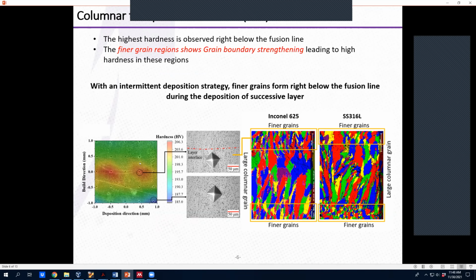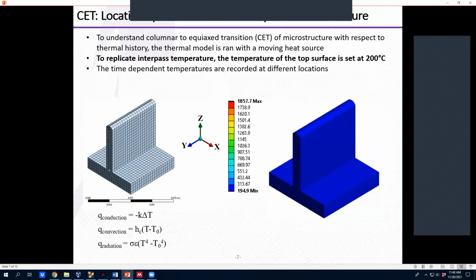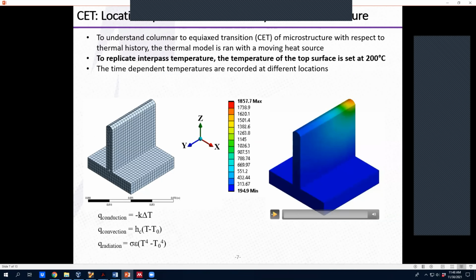With the location cleared out, the next question is why the fine grains are forming right below the layer interface. To investigate that, we took the help of thermal modeling. We are trying to simulate the thermal history of our deposit, using a quite simplified geometry, a thin wall structure. We run a heat source on the top surface of our structure, and from this thermal simulation, we record the temperatures at different locations. Based on those temperatures, we do our further calculations.